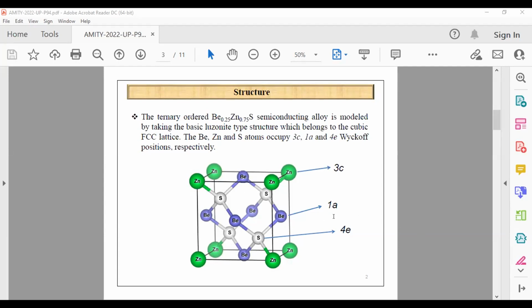So we can see that there are three beryllium atoms, because each face atom in the middle face is shared by 2 unit cells. So we can say that there are 1 Zn atom and 3 beryllium atoms and 4 sulfur atoms. And the Wyckoff positions of beryllium, Zn and S are 3c, 1a and 4e. So this is a basic structure which belongs to the cubic space group, and its space group number is 215.